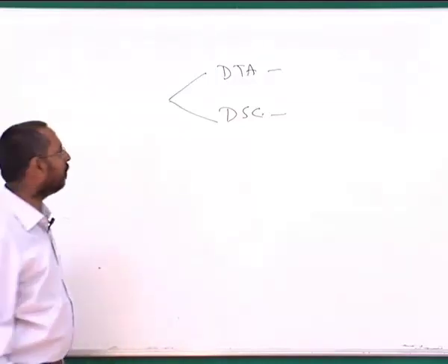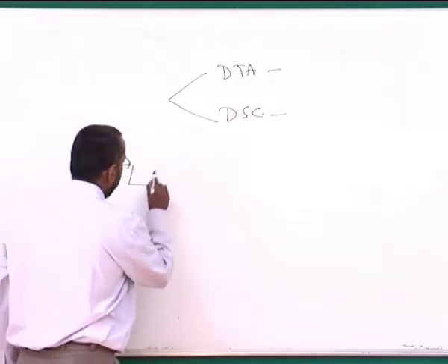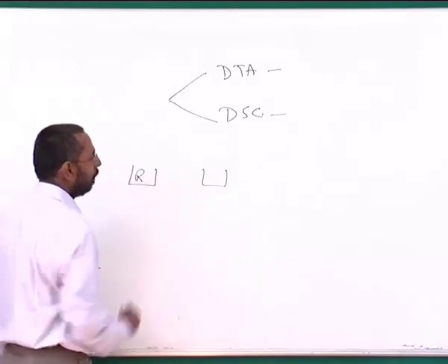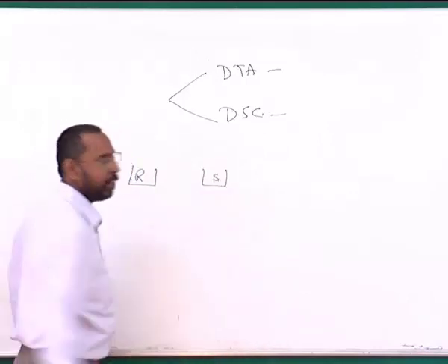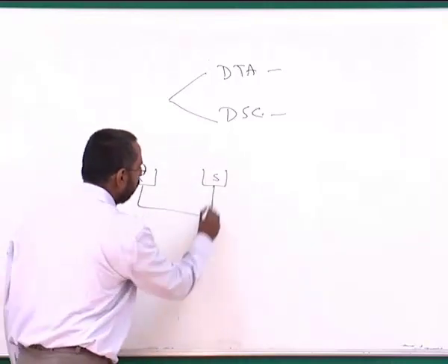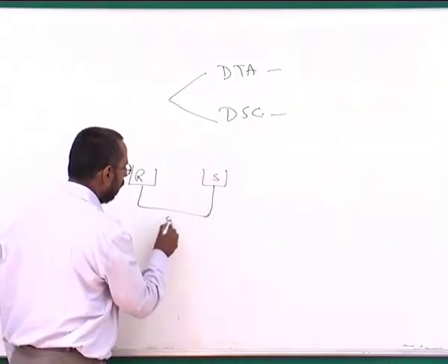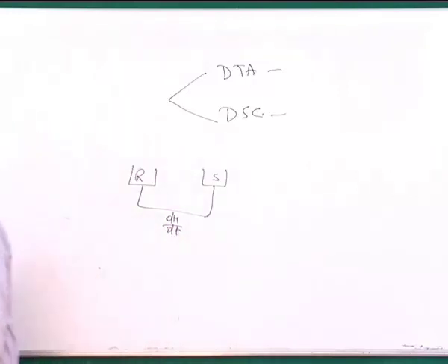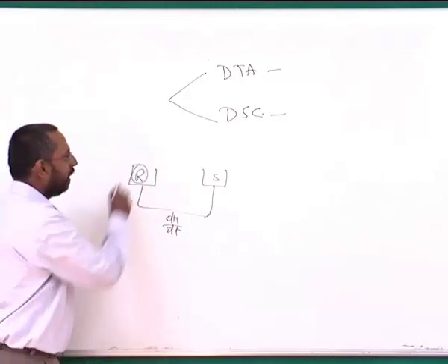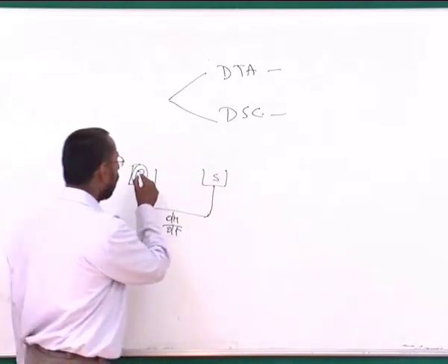So what we do in this is, you have two sample holders, where you put one reference sample in one holder and your sample in the other, and keep on heating both at a particular heating rate, a certain dH by dt. And you make sure that your reference sample is such that in the temperature domain of your interest, it does not undergo any phase transformation.